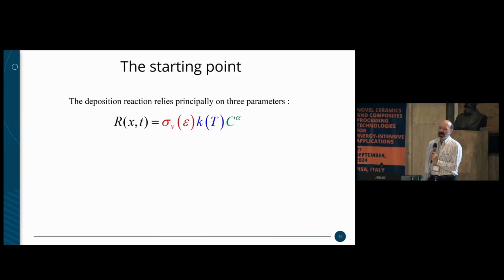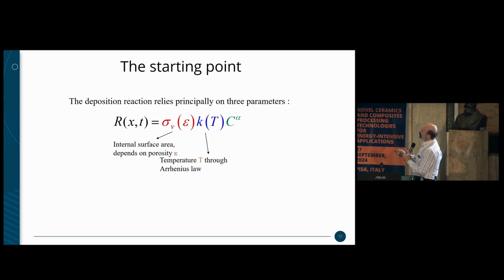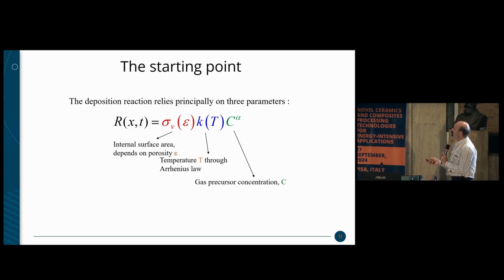Okay? The starting point of modeling and understanding this affair is the deposition reaction. Locally, in any point of your preform, the deposition reaction relies on three parameters. The internal surface area, which is a function of porosity, the rate law here, which depends on temperature through Arrhenius laws, and the gas precursor concentration here. So if you do so, you need three variables at least to describe the reaction zone.